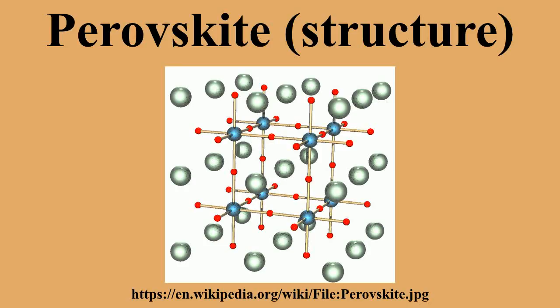Although the most common perovskite compounds contain oxygen, there are a few perovskite compounds that form without oxygen. Fluoride perovskites such as NaMgF3 are well known. A large family of metallic perovskite compounds can be represented by RT3M, where metalloids occupy the octahedrally-coordinated B-sites. RPd3B, RRh3B, and CeRu3C are examples. MgCNi3 is a metallic perovskite compound that has received a lot of attention because of its superconducting properties. An even more exotic type is represented by mixed oxides of Cs and Rb, such as Cs3Au2O, which contain large alkali cations in the traditional anion sites, bonded to O2- anions.